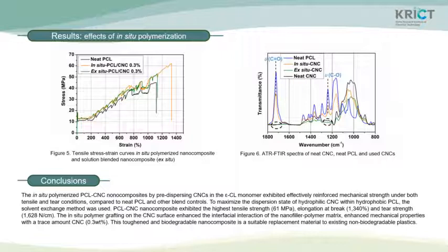To investigate the CNC surface modification of PCL-CNC nanocomposites, excessive CNC, which is 5%, was in situ polymerized to PCL-CNC nanocomposite and solution blended with the homopolymer in chloroform. And then used CNCs were separated out from the polymer part. The chemical structure of the used CNC was identified by FTIR, and you can see the result in figure 6. High molecular weight polymer portion of solution blended CNC was easily removed by centrifugation. But the in situ polymerized CNC showed many polymer fingerprints, indicating a covalent linkage with nanofillers. This means the esterification of hydroxyl groups on the CNC surface occurred during in situ polymerization.